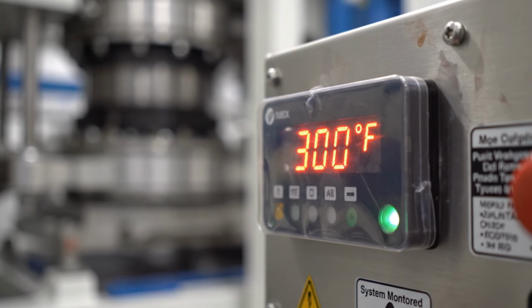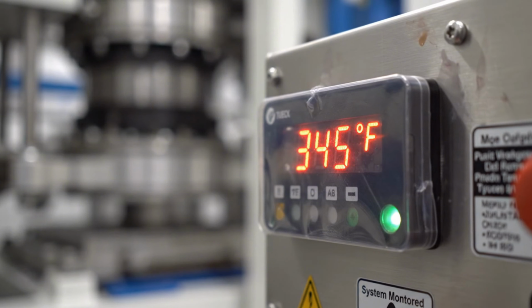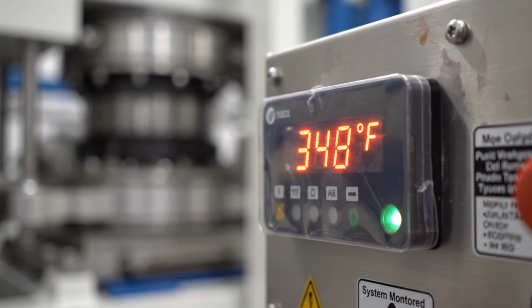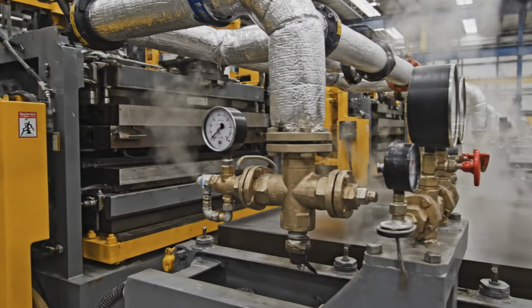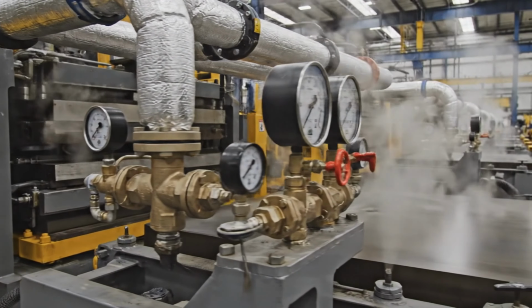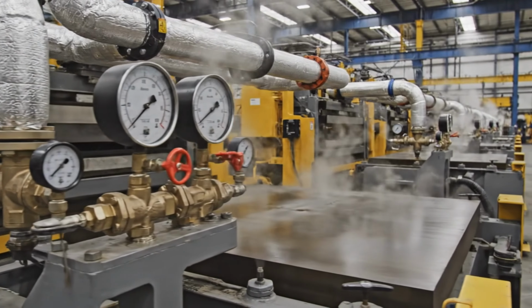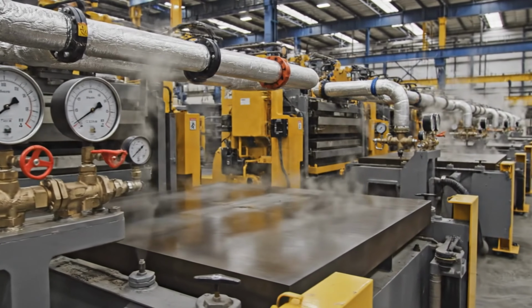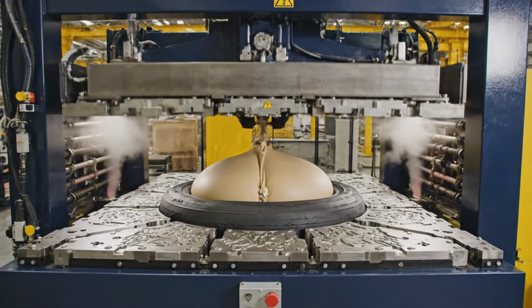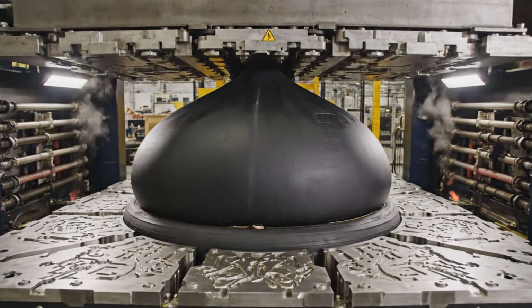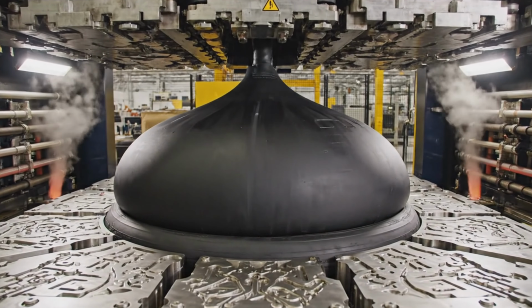Curing temperatures typically reach 300 to 350 degrees Fahrenheit, high enough to drive the vulcanization reaction, but not so high as to damage the rubber. Steam systems supply the heat for vulcanization. High-pressure steam flowing through press platens maintains the precise temperatures needed throughout the curing cycle. Bladder systems inflate inside the tire during curing, pressing the rubber against the mold.